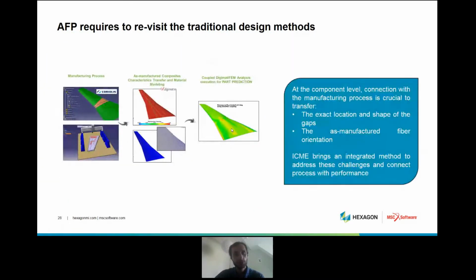In summary, at the component level, like the wing that we have here, the connection with the manufacturing process is really crucial because it enables, on one hand, to transfer the exact location and shape of the gaps, and on the other hand, the as-manufactured fiber orientations, which can change versus an idealization of the part. And with ICME, we have an integrated method to address those two challenges and truly connect the process with performance through the material model, which is sensitive to the microstructure.